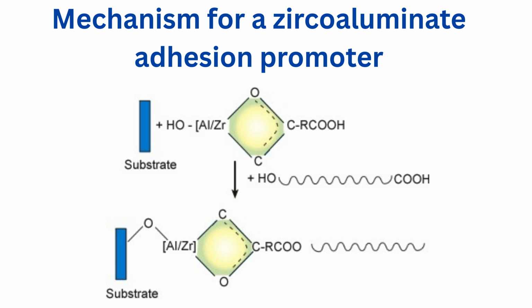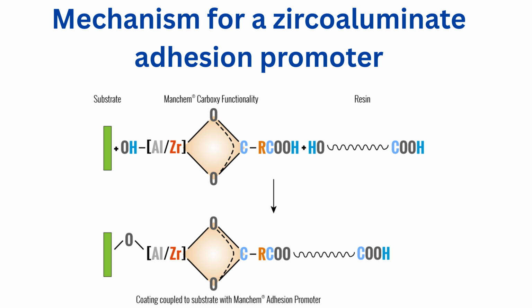Zircoaluminates. Zircoaluminates emerged in 1983 as a new class of metal organic adhesion promoters. They are highly reactive with a diverse array of substrates and do not suffer from the hydrolytic sensitivity of the silanes. They improve wet adhesion and reduce concomitantly corrosion on metal surfaces when incorporated into solvent or waterborne coatings. When incorporated into adhesives or rubber compositions, they improve their bond strength to difficult substrates. Hydroxy-bridging linkages are formed between the zircoaluminate and sites on the metal surface. Subsequently, the zircoaluminate carboxy group undergoes condensation with the resin terminal hydroxy groups, resulting in chemical linkage of the resin to the substrate through a zircoaluminate chemical bridge.